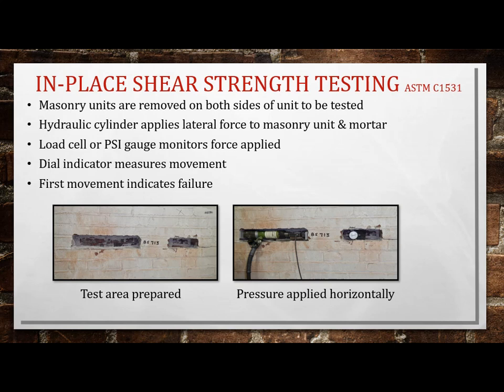So this is the test where you remove 2 bricks. The brick in the middle is like number 713. That's the test brick, right? So you remove 2 bricks behind it and a brick in front of the test brick. You put in a hydraulic ram that's a calibrated system with a load cell, and on the right side of it, you have a dial indicator that measures movement. As you pump your system, you apply force to the side of that brick. You're trying to push that brick sideways, and what's resisting it is the bond strength of your bed joints.